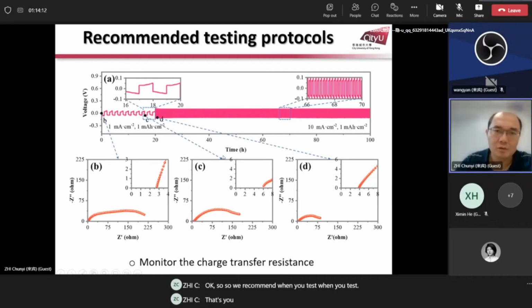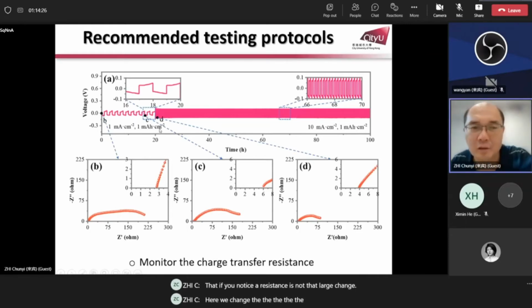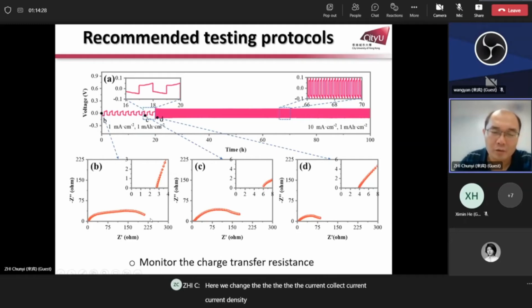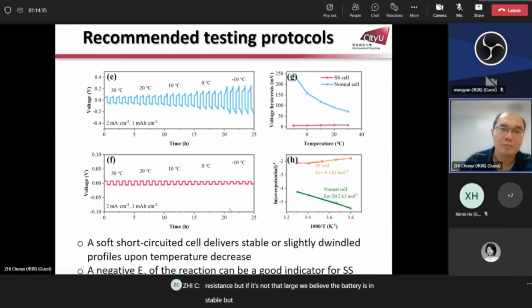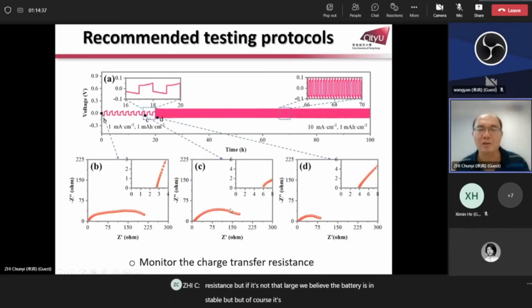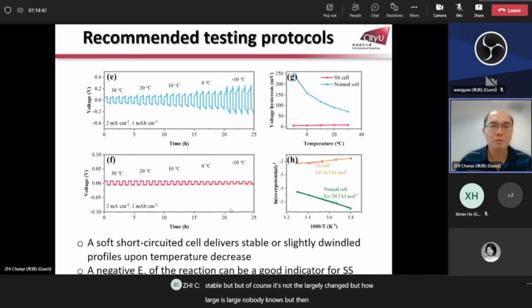Okay, so we recommend that during the cycling test, you need to measure the impedance. If you notice the resistance is not that large a change, here we change the current density. Although you see some change of the resistance, if it's not that large, we believe the battery is stable. But how large is large? Nobody knows.